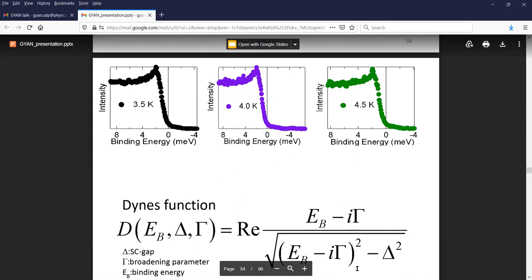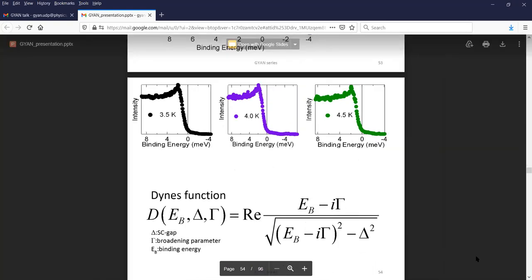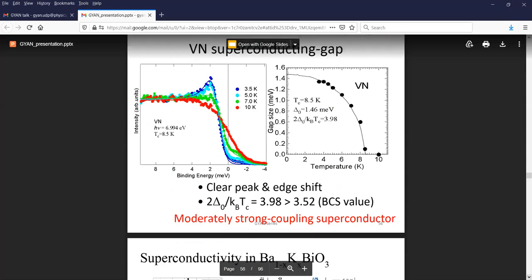The function used is called the Dynes function — given by the real part of a particular equation. One can calculate and see data with the red lines as fits, getting a weak feature even just above the Fermi level — the BCS model has a peak above the Fermi level that gets populated at higher temperatures. One can get a match with the BCS model behavior — BCS theory with moderately strong coupling: 2*delta-naught/(k_B * TC) = 3.9. One can also do this for an oxide superconductor, and the full valence band spans zero to six electron volts while the superconducting gap states are very low intensity near the Fermi level. An Eliashberg analysis of the superconducting density of states is also possible.